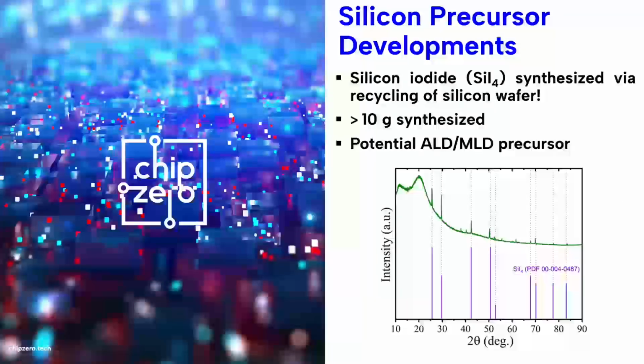But the main idea is that everybody is aiming for lower dielectric materials, where we could develop silicon oxycarbides, and other precursors are not that easy to treat with organics. So we are aiming for ALD and MLD, atomic layer and molecular layer deposition, using this silicon iodide to develop some low dielectric materials.